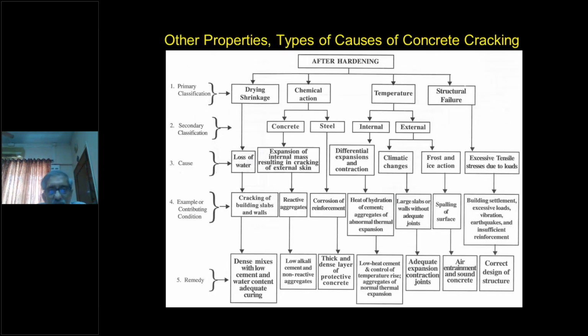Other types of causes of concrete cracking after the concrete has hardened. Now mind you, concrete will harden either within a few minutes depending on the ambient temperature, or it will sometimes take days. But generally curing is specified for 7 days. If you are using pozzolanic cement or pozzolanic material like fly ash and slag, then IS recommends longer curing periods, maybe even 14 days.